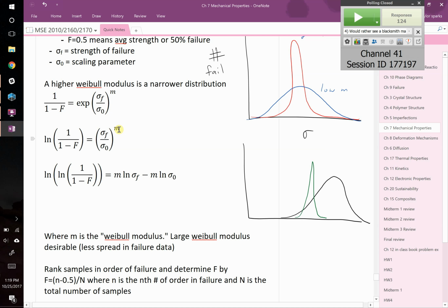This is surprising, right? This basically says that of these two materials, if you care about things surviving at really, really low probability of failure, you should use the material that on average is weaker, because it has a tighter distribution. That's very surprising. If you did your whole gut-feel thing, you're not going to get close. First off, you'll have no idea what stress it can go up to for some probability of failure like 1 in a million, and you would probably never guess that material would be better than the other one. But here we've definitively shown that the material that was weaker on average but had a tighter distribution can withstand 3 times the strength of the other one with the same survival rate. Which is pretty awesome, right?